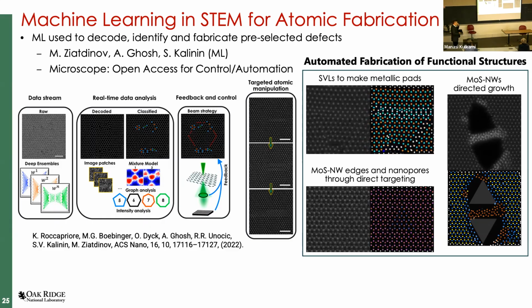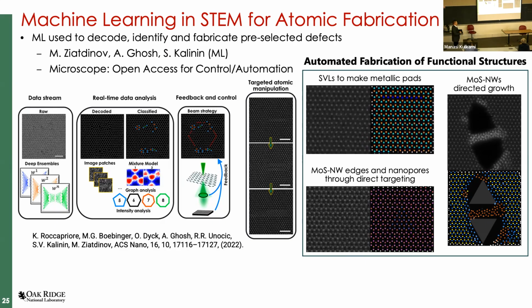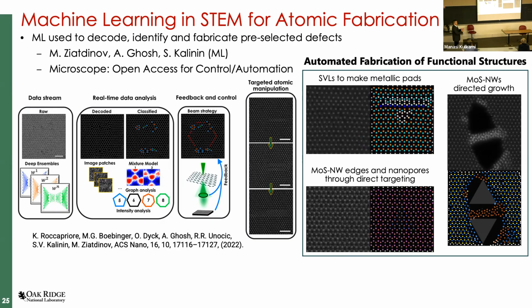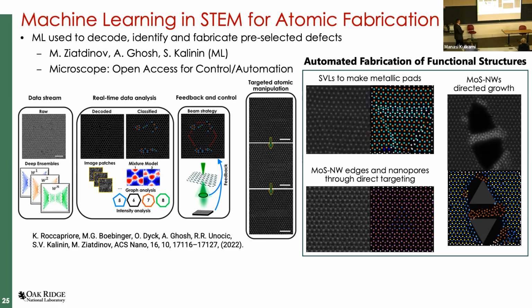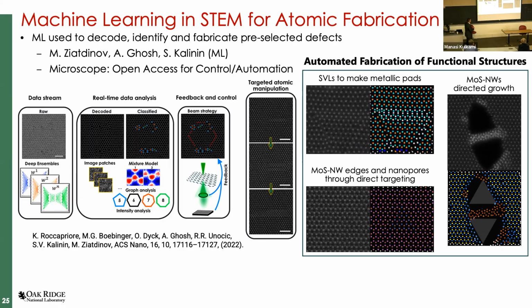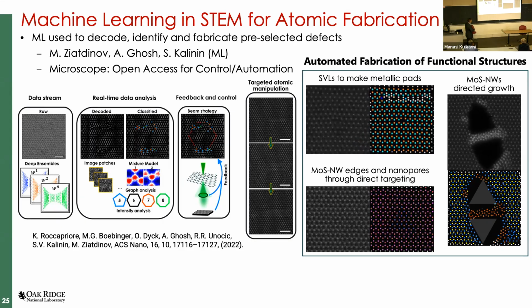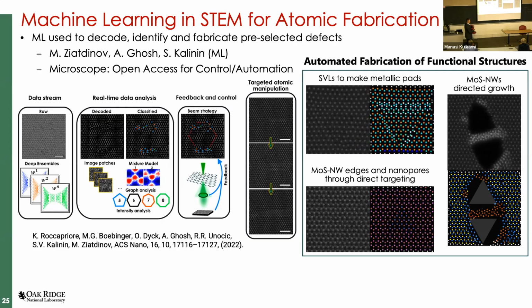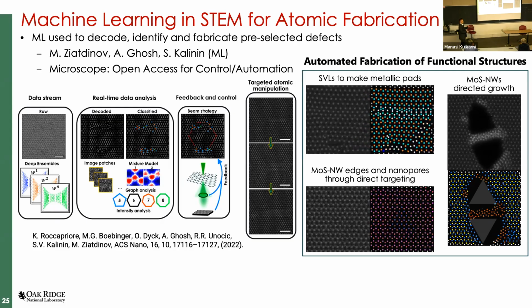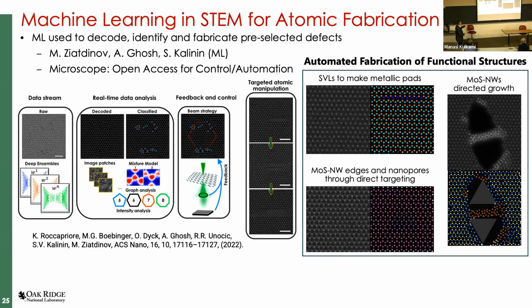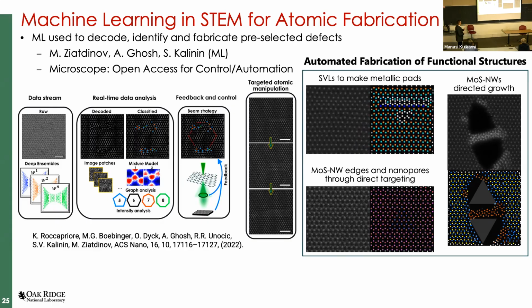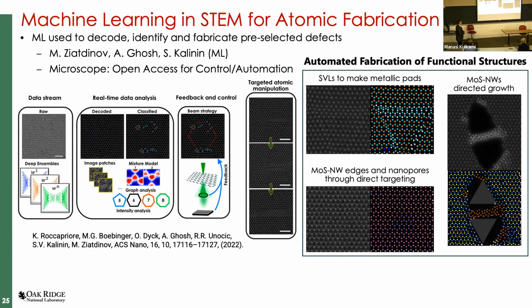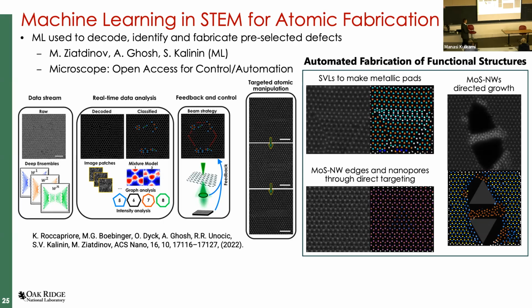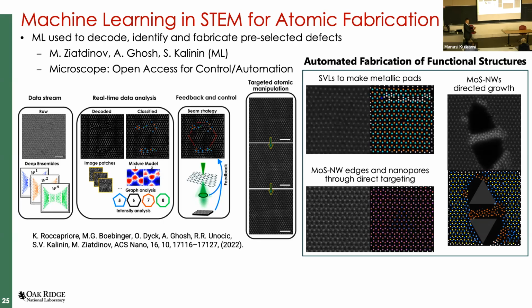So it took a while for my postdoc to come up with the training models for molybdenum sulfide, to figure out which defects you're forming. But if you look closely, this is pretty interesting. If you take a 2D material, the molybdenum sulfide, the bright atoms that you can see quite readily, you can see it a little bit better on the laptop, the bright atoms are the moly, the less intense ones are the sulfur stacked on top of each other. And what you're starting to see right here is you have a collapse in your lattice.